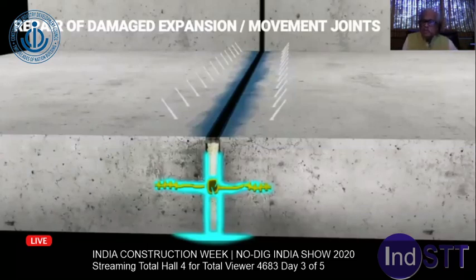Some physical barrier should be put. If they have not put a physical barrier, and if your width is 60 centimeters, you can put some Cyrodex board up to, say, 30 centimeters. So automatically you get a physical barrier. Go behind that 30 centimeters at a 45 degree angle and inject a gel inside it. A little bit of gel will come out because there is no sealing with the thermocol or Cyrodex board or dimple boards. Some material will go there. It is good for you.